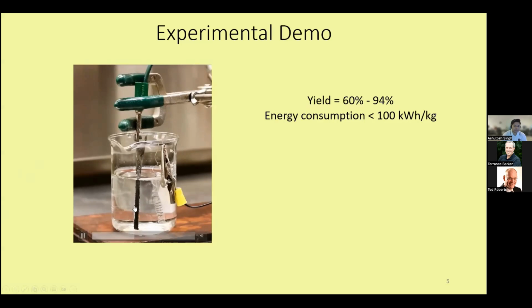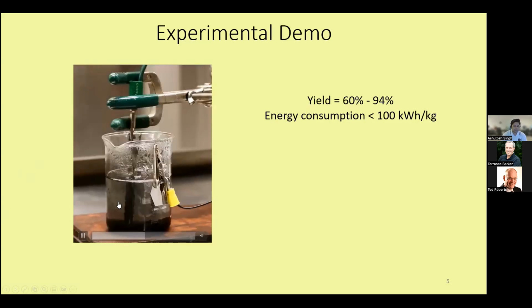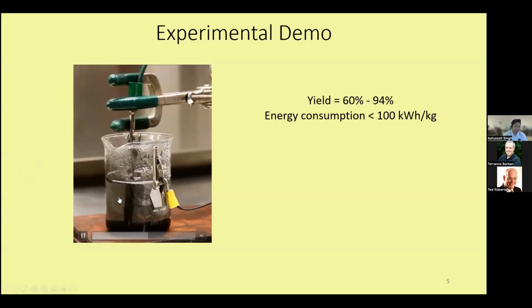And as we go forward, you can see more and more layers moving up out of this graphite material. And so here you can clearly see that after a couple of minutes into the reaction, the graphite is completely consumed and you start producing a whole bunch of graphene. There is also some unexfoliated graphite that has to be separated out.